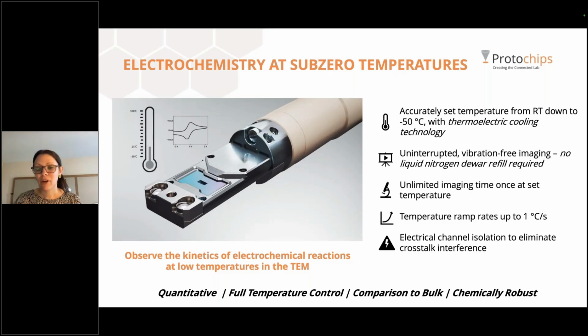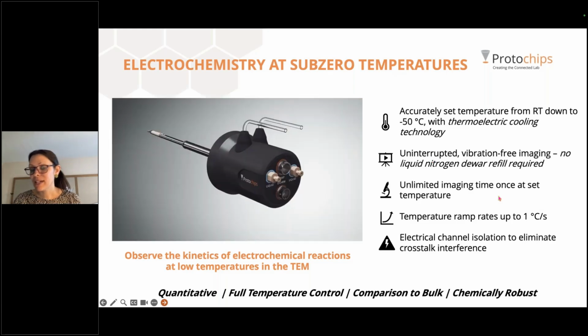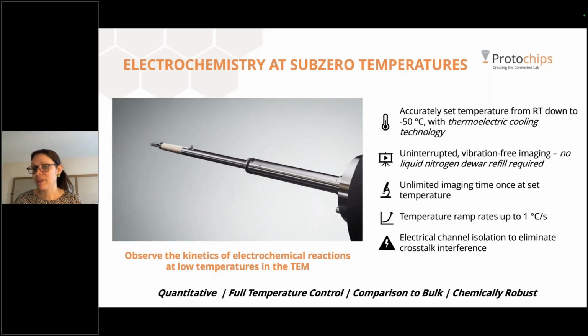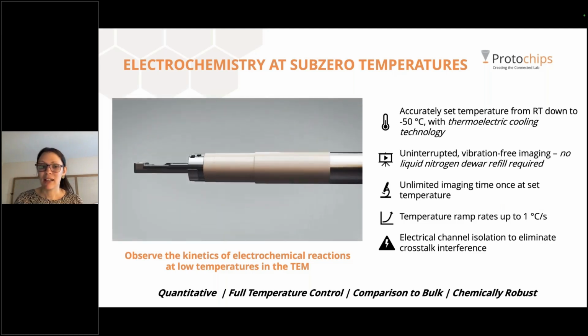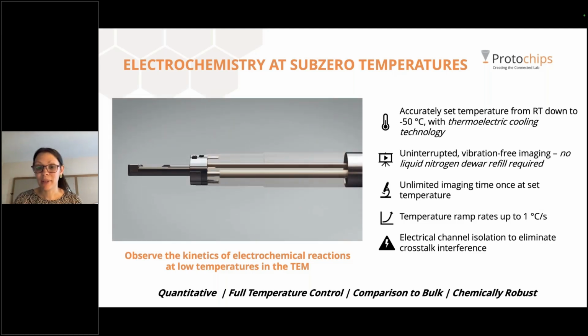Now, you don't have to go to that minus 50 degrees C. You're not bottoming out like you would with cryo, where you usually have to go to the coldest temperature. You do have control over that temperature, and I'll show you how the cooling works together with the heating to do that modulation. But because we're not using liquid nitrogen, you don't have a dewar to refill, hence the unlimited imaging, unlimited stable imaging as well.